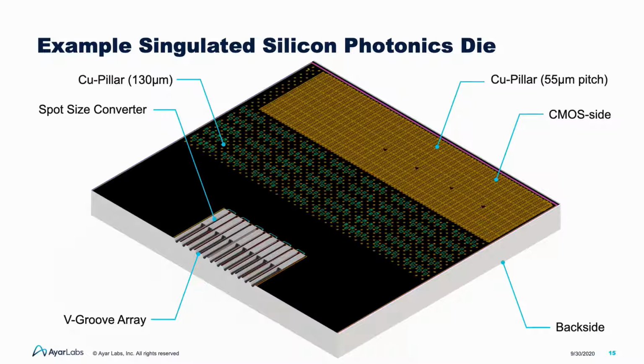This is an isometric scaled drawing of a singulated teraPHY die, roughly 8 mm on a side. 55 micron pitch copper pillars can be seen in the upper right section of the die, while 130 micron pitch copper pillars can be seen in the center of the die. Note that this combination of copper pillar pitches is not a limitation of teraPHY.